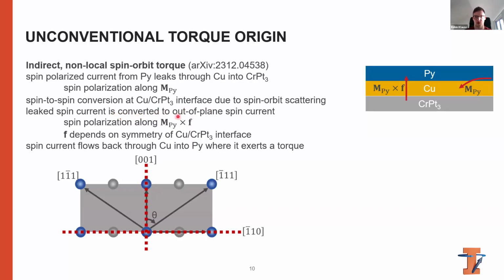So spins get converted from one polarization and travel direction to another. The current is converted to an out-of-plane spin current, where the spin polarization is along the magnetization of permalloy crossed with this vector F. This vector F depends on the symmetry of the chromium platinum 3 copper interface, so with different symmetries, we get different vectors F, and then different spin polarizations.